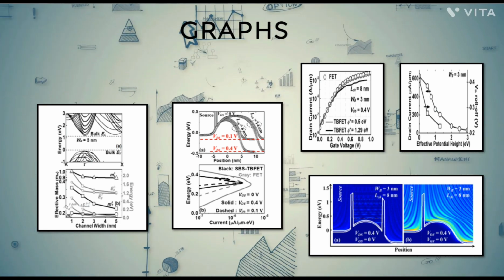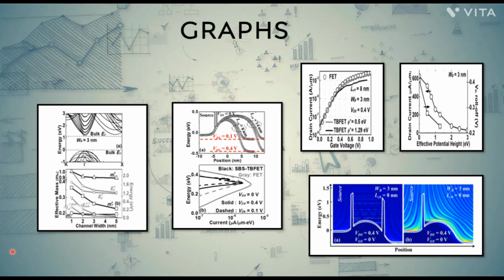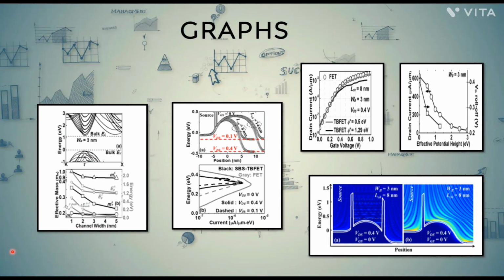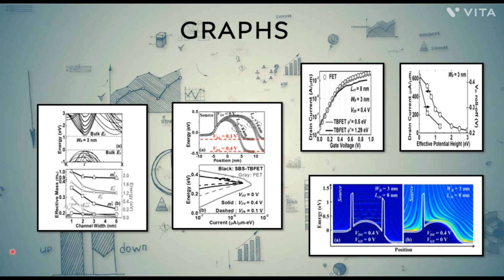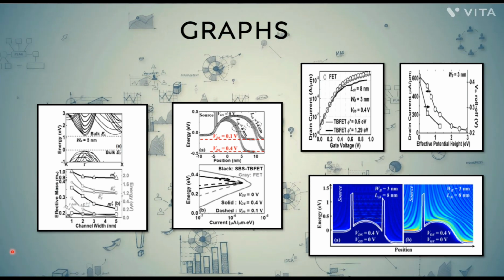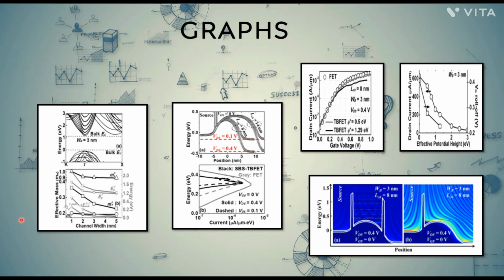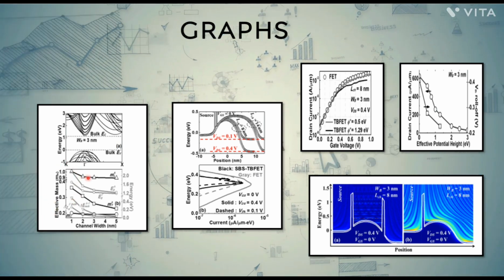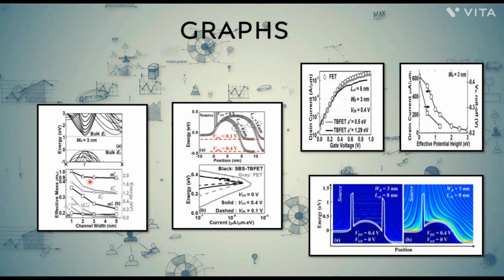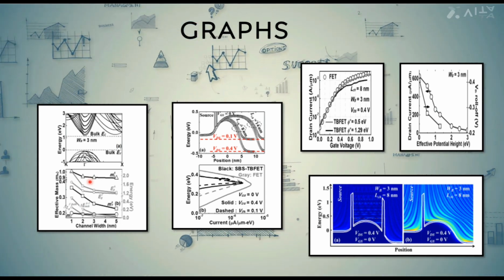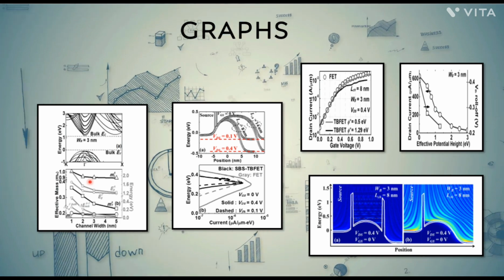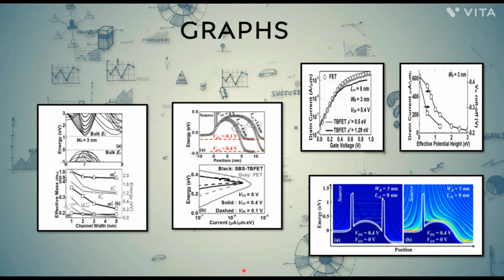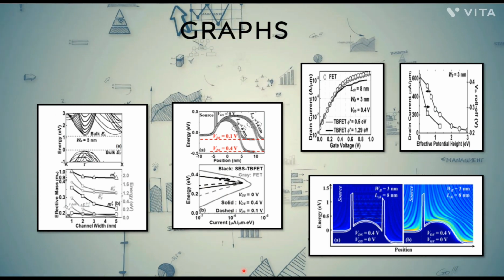So first, this picture infers the electronic band structure of silicon slab terminated by hydrogen atoms on the surfaces, where the band gaps and curvature effective masses can be determined by the gamma and delta points which are shown in the figures. So band gap, curvature effective masses, the two lowest subband energies, and the electron affinity differences with respect to the bulk values with various WB values. So the next graph gives the lowest subband profiles of the FET and SBS TB FET.